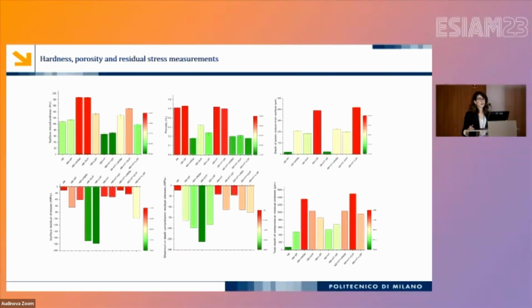As expected, all the treatments that are based on plastic deformation are enhancing the surface micro-hardness, or let's say the micro-hardness of a layer close to the surface. They are slightly reducing the porosity because they are closing the pores that are very close to the surface. So the subsurface pores are being closed because of the plastic deformation that is induced on the top surface layer. And we have also compared the depth of the layer that is related to the closure of the pores with respect to the surface. You can see all the treatments are introducing pore closure, but to different extents with respect to the mechanism that is involved there.